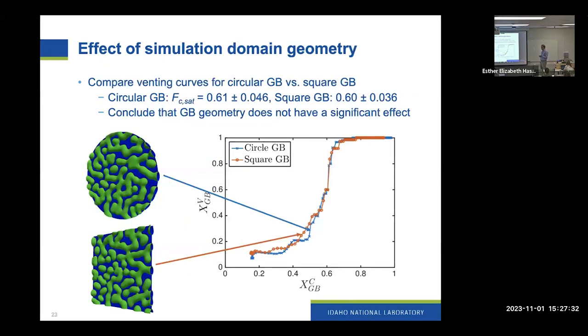Another thing that we looked at, there were several other factors that we looked at. I think one of the more interesting ones is the effect of the simulation domain geometry. This square shape for a grain boundary is not really representative of the number of edges of a typical grain boundary. So we said, okay, what's the other extreme to that? It would be a circular grain boundary, right? And so, a different ratio of area to perimeter, kind of two extremes.